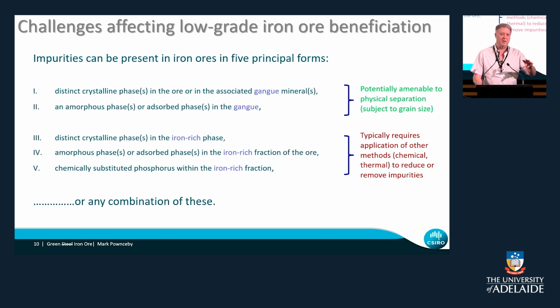So the key problem that I think I see here, and this is dictating why a lot of our approaches so far have been challenging, is the effect of impurities. And it depends on how your impurities are in the iron ore. If there is a discrete phase, like a clay in an aluminosilicate phase, or perhaps in the case of phosphorus, it might be adsorbed onto aluminosilicate clays, we can probably separate that fairly easily using traditional techniques. They're discrete phases, they're not interlocked, we should be able to separate those.